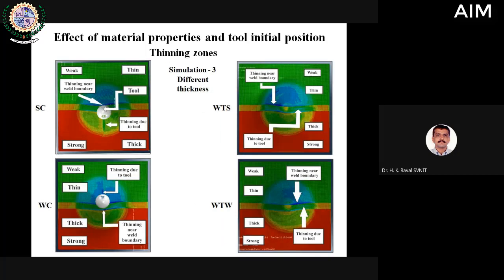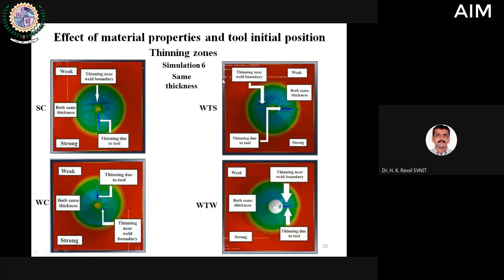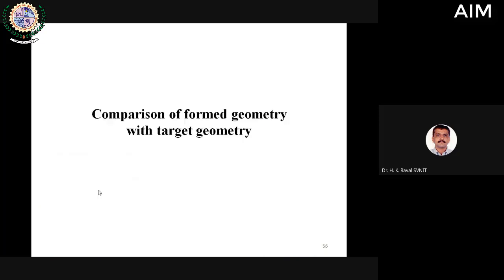Then this is the result of simulation number 3 out of 9 simulations. This is the result of simulation number 6. Simulation number 6 is very clearly indicating the thinning on the weld line. You can see, because the starting position is on the weld line. Thinning on the strong center, thinning on the weak center. That is because the starting position is strong and weak respectively.